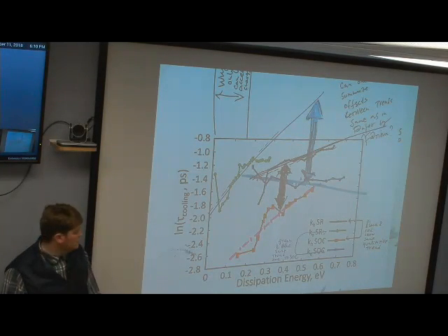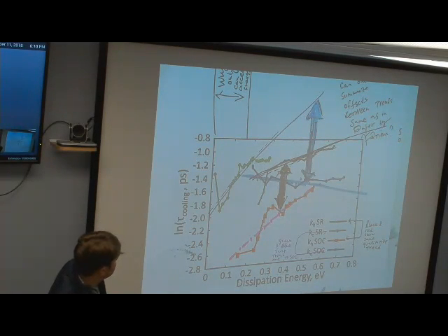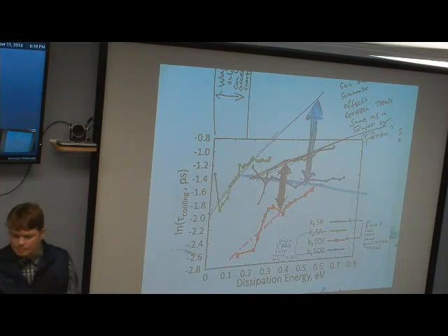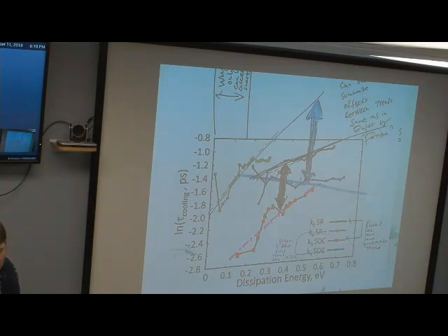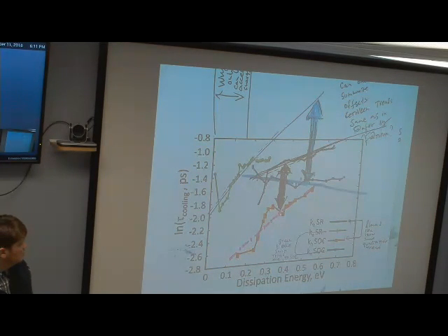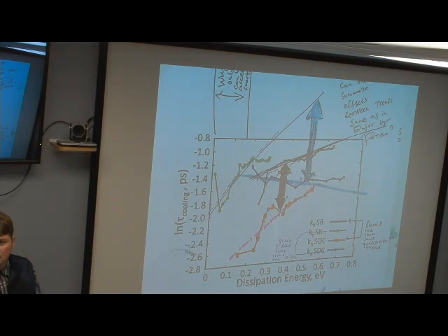You said the green one and the, say, red one or black one? Red one. So for the whole states, there's usually between HOMO minus one and HOMO a decent sized subgap. So that might explain why if you just populate HOMO minus one initially, it deviates from the rest of the trends. But the green one, there's not a subgap, so I guess I don't know. We could just say it's not the right basis to describe electrons, since there's strong spin orbit coupling.